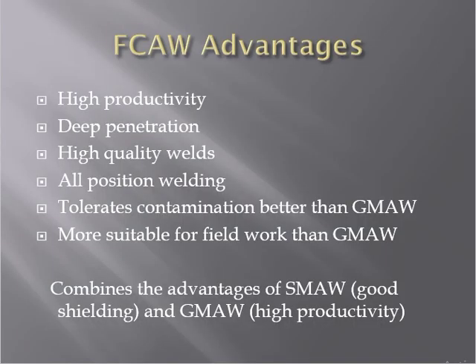The advantages of FCAW include: high productivity — enabling welding over long areas; deep penetration, providing good weld strength; high quality welds; all-positional welding capability; better contamination control than GMAW; more suitable for field work than GMAW; and it combines the advantages of both SMAW — good shielding — and GMAW — high productivity.